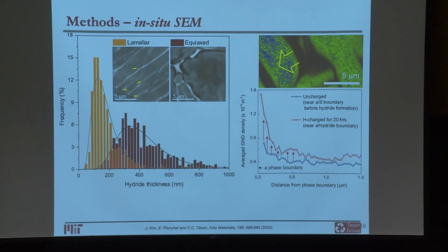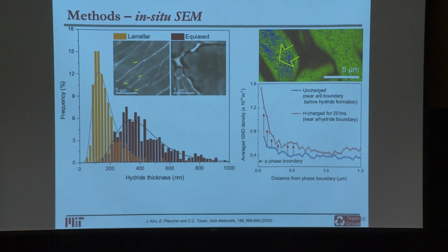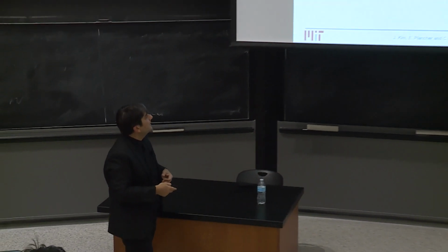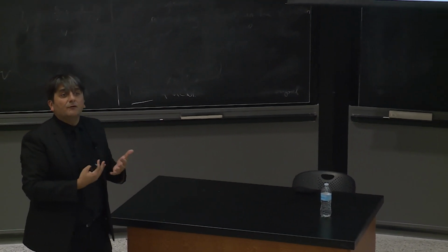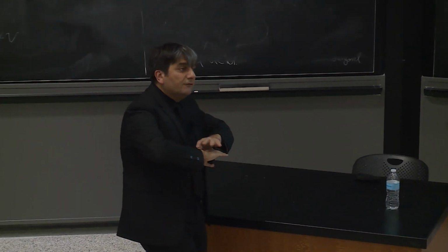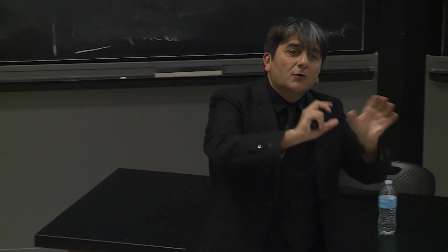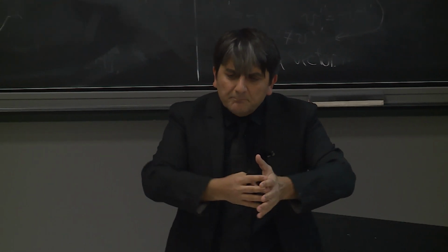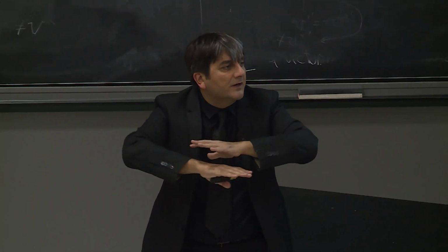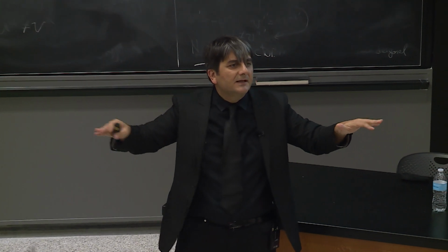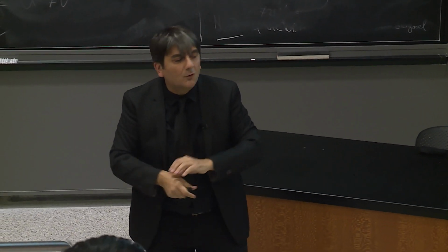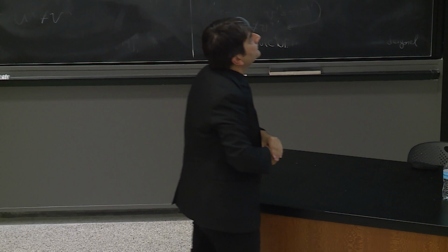So all this basically tells us, by doing this analysis in a complex-looking microstructure, that in Ti-64, it would actually be much better to have a fully lamellar microstructure rather than a combination of these thin beta phases and the thicker beta phases. And the idea there is very simple. You are creating many highways for hydrogen to diffuse, so you are essentially dispersing hydrogen and effectively reducing its local effects and reducing the embrittlement. All right, so in the in situ SEM charging mode, you can also learn more.